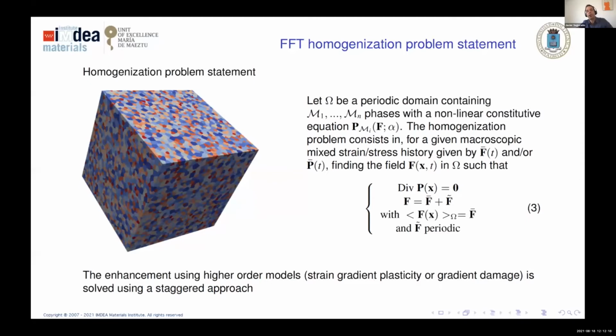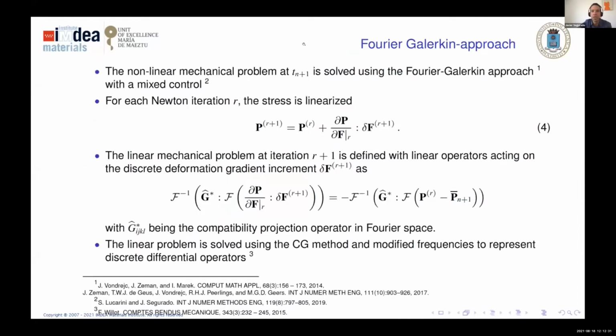And how we couple that with higher order models, we do it using a staggered approach. We solve this problem, and then we solve for the enhanced higher order problem for the coupled equations, and we do it until we get convergence. In terms of the Fourier solver, we are mainly focusing on the Fourier-Galerkin approach developed by Jan Zeman, Vondřejc, and co-workers, and some others, that we have combined with our own method to impose mixed boundary conditions. So we do not have to iterate to obtain uniaxial stress, but we can directly impose free stress or some given stress in some directions within the problem.